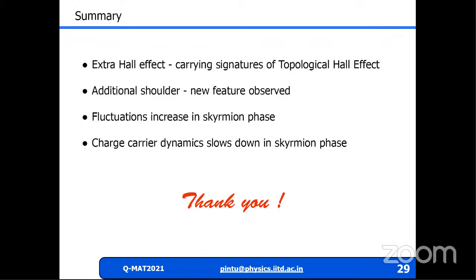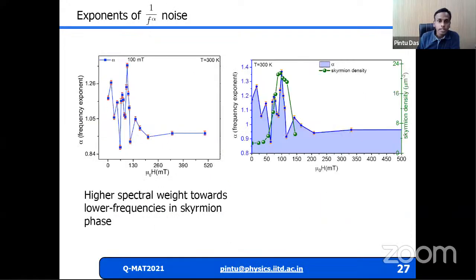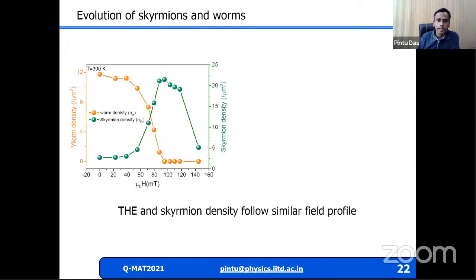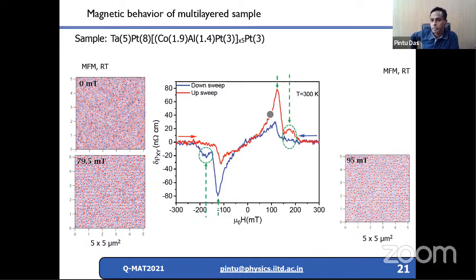You said towards the end of your talk that your skyrmion seems to be not moving around or is frozen. Have you ascertained whether it is pinned because of impurities or defects, or is it actually forming a reasonable lattice? Any comments on that? The reason I said that they are not moving is that the critical current density required to really move these skyrmions is much higher than what we apply. We have not personally done the experiment to observe the motion, but as we know, the critical current density is of the order of 10 to the power 12 ampere per meter square to really see the skyrmion motion.